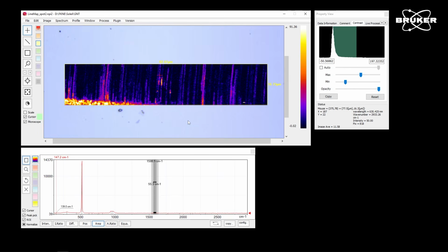Carbon nanotubes are relatively weakly scattering, and if you have them just as powder or so on, they are extremely fragile, and here the laser line mode, on these silicon substrates but also if you have them in other conditions, really improves the minimization of sample damage, because with a laser point source, you easily break these nanotubes and destroy them.